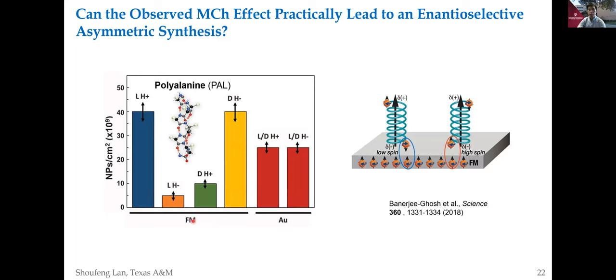When the magnetic field is up, or H plus, more left-handed molecules, or L molecules, will be attracted to the surface. While when the magnetic field is down, or H minus, more right-handed, or D molecules, will be attracted to the surface. There's no such asymmetric adsorption on a gold surface because gold is non-magnetic. They attribute this phenomenon to the interaction between the spin from the ferromagnetic substrate and the spin current from the chiral molecule, which is exactly a spin or electronic version of the pseudo-scalar. That is why we think it's promising that our magneto-chiral effect will also induce such a phenomenon.